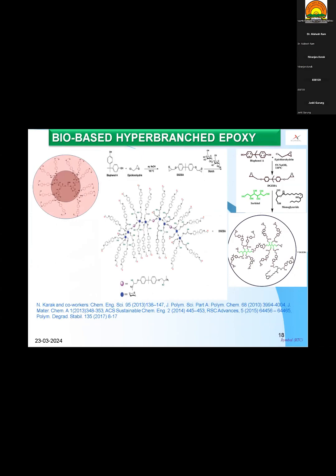Epoxy adhesive has very good adhesive strength, but the problem is their brittleness. They are not tough. They are not biodegradable. So how to achieve this biodegradability and toughness? For this, our researchers started to get hyperbranched bio-based epoxy resin. And we have seen that incorporating a suitable bio-based moiety into the system like monoglyceride of castor oil resulted not only in highly impact-resistant epoxy thermosets, but also it will give you biodegradability.